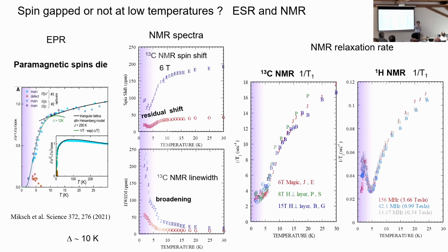It's an indirect field. But in this case, the molecule-to-molecule overlap is very small. So if a spin 1/2 is sitting in the neighboring molecule, this local field is very, very small. So in the molecular materials, carbon-13 has a nearly negligible Q dependence.